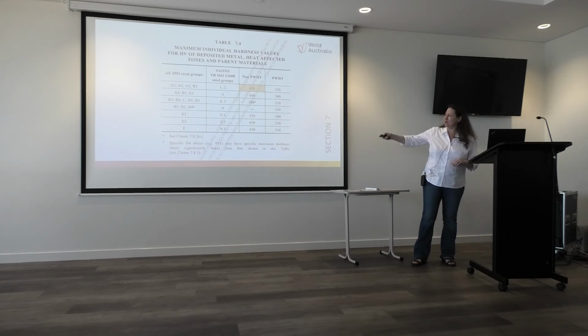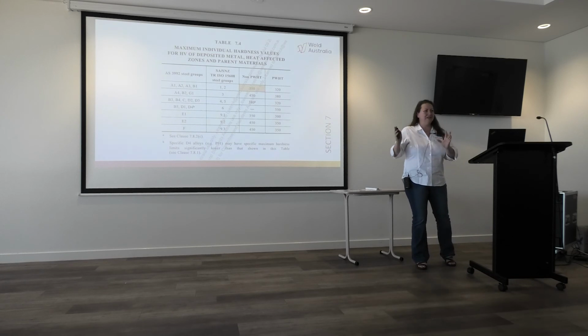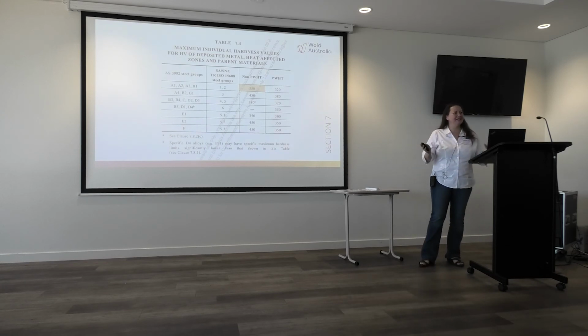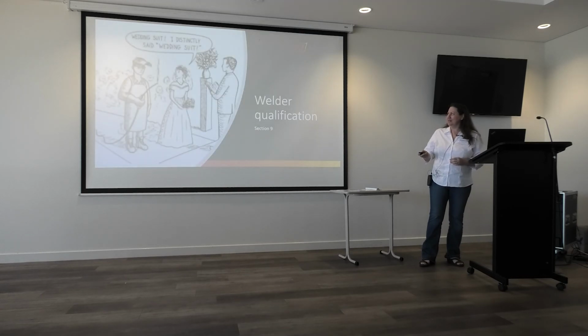But everything else is for the different material groups. And you can see where there's a line, it doesn't mean there's no requirement. It means that these materials you don't use in the unpost-weld heat treated condition. I wanted to add that line into the standard, but they said it was overkill. So, welder qualifications, and this poor welder had a misunderstanding with his bride.